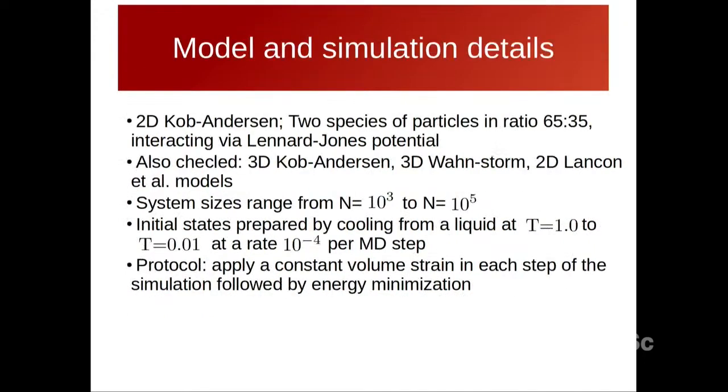What we are doing is particle-based simulations. We are using the standard 2D Kob-Andersen model, which has a Lennard-Jones potential, and you have particles in a 65-35 ratio. We have also checked this phenomenology for many other models in 2D and 3D. We prepare an initial glass by cooling a liquid in MD simulations from a high temperature to some low temperature at some cooling rate. We have checked a few more cooling rates as well, but the phenomenology is broadly the same.